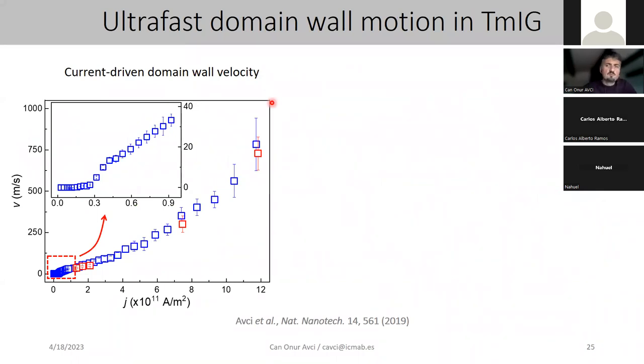And finally, we wanted to move these domain walls fast with current. So I'm showing you here the velocity versus current in this thulium iron garnet/platinum bilayer. And there are two striking features. First of all, the domain wall velocities are quite fast. It's reaching 800 meters per second, and it's quite linear with current. And the transition between the creep regime and flow regime occurs at an extremely small current density, in the order of 3 times 10 to the 10 amps per meter squared. Both the velocity and these numbers are quite high, or let's say close to state of the art at that time